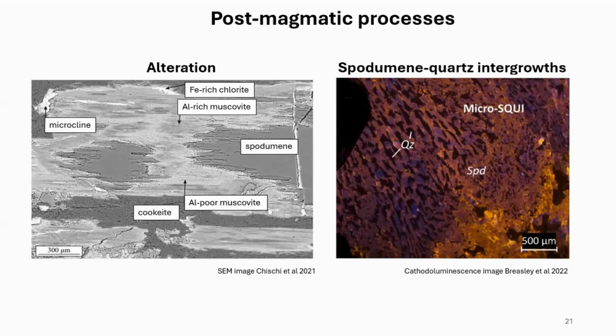So the real problem with alteration of spodumene is metallurgical. So if you've got a property, right, and somebody's reporting, well, it's 1.2% Li2O, that really looks good. If you haven't done any studies of the spodumene, if it's not fresh, it's a problem. You won't get it through the mill. Like you'll get it through the mill, but you'll either have to crush it to less than 100 microns, that's really expensive, or if you try to heat it, it's going to gum up because the muscovite is going to form glass, these coatings, thin layers around the spodumene grains. So alteration is a big problem in mineral processing for spodumene.